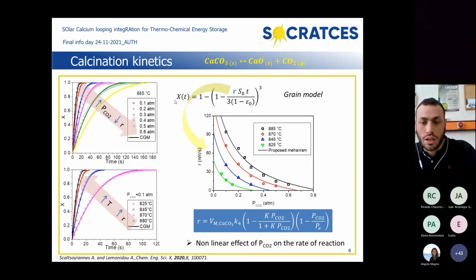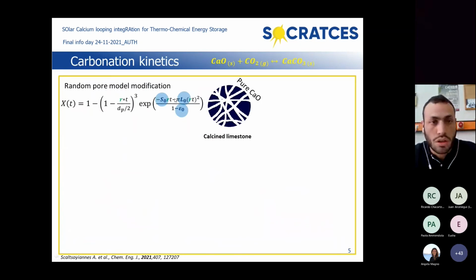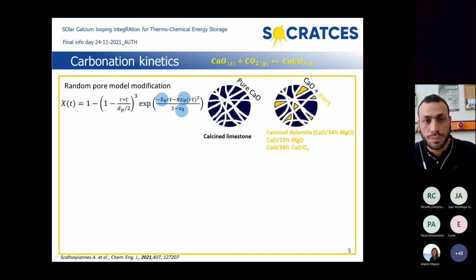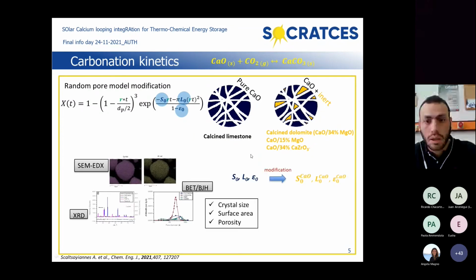This is for calcination kinetics, and for carbonation kinetics, we use the random pore model, which is a similar geometrical model to the previous one. Again, we have some input parameters that are related to the surface area and the porosity of the materials. But in this case, we try to expand this model in order to apply it to materials that contain an inert phase also, apart from the calcium oxide phase. And this was done by modifying these input parameters.